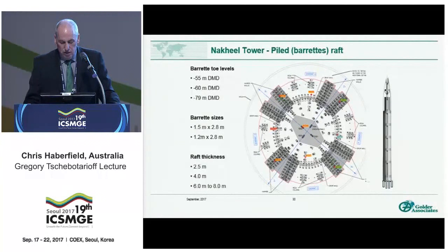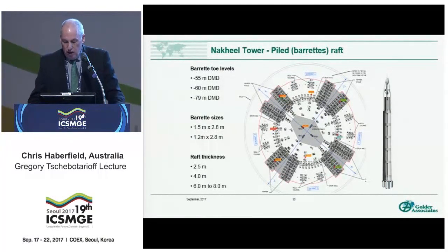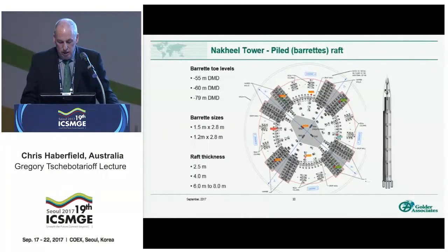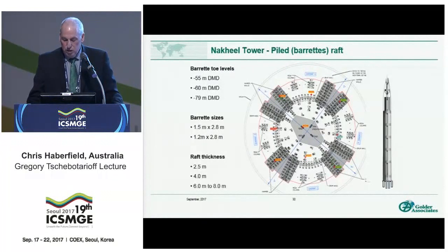below ground surface. The number of barrettes finally adopted was significantly more than was indicated from our soil structure interaction analysis, as a local authority required a factor of safety of 2.5 on every barrette. Even after numerous meetings, we couldn't convince them to relax this criterion. The length of the barrettes compared to the height of the tower is shown to the right of the screen. The raft thickness varied between 2.5 metres and 8 metres depending on location.